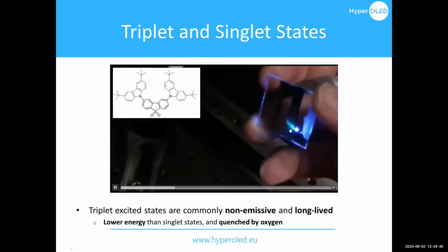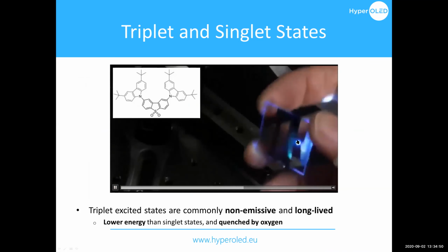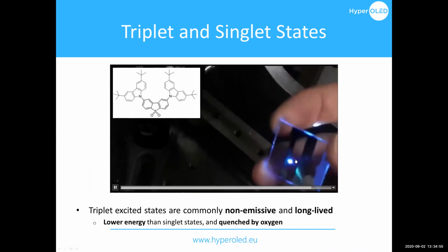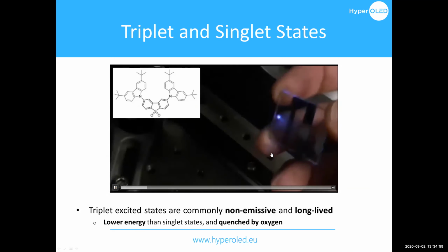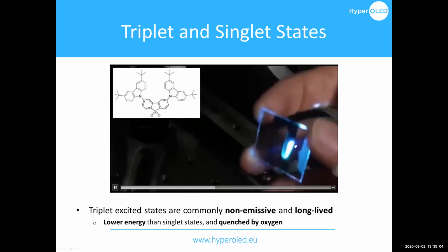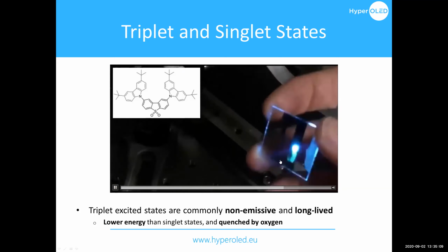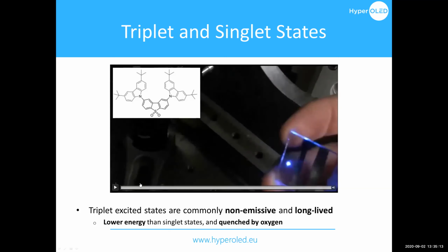In this video, we've got a laser point hitting a material that undergoes both fluorescence and phosphorescence. In the clear parts where it's not protected from oxygen, the triplet states get quenched relatively quickly, and we only see the higher energy blue emission. Whereas with the aluminium backing, you also get the triplet emission of phosphorescence, and you can see how long it really lives. To get lifetimes on the order that you can observe with unaided sight is pretty interesting when you think about it for purely electronic transitions.